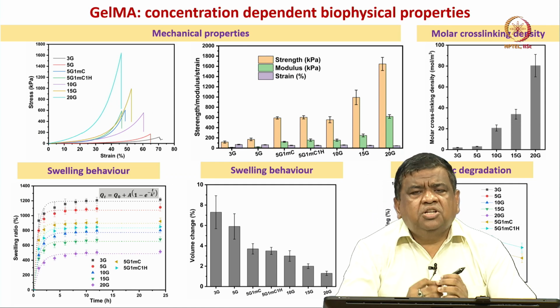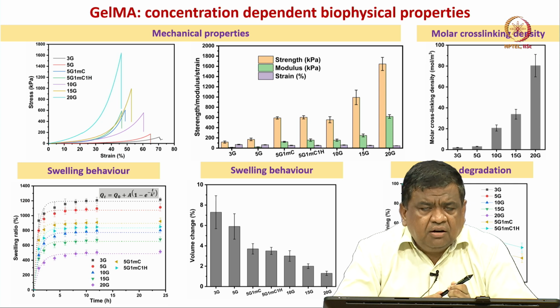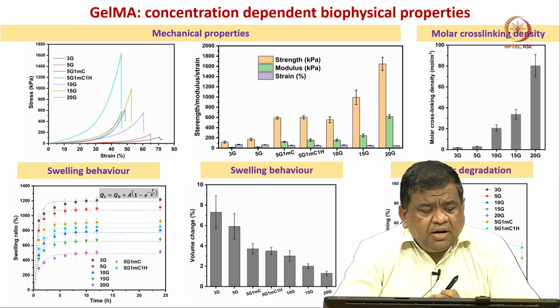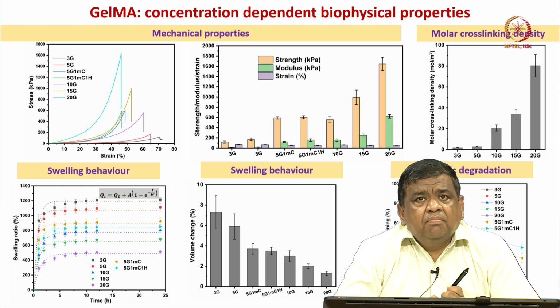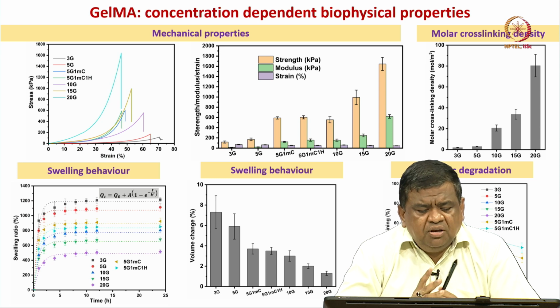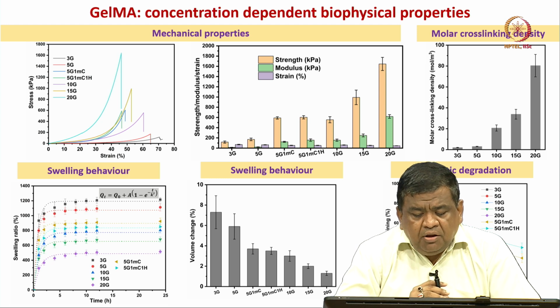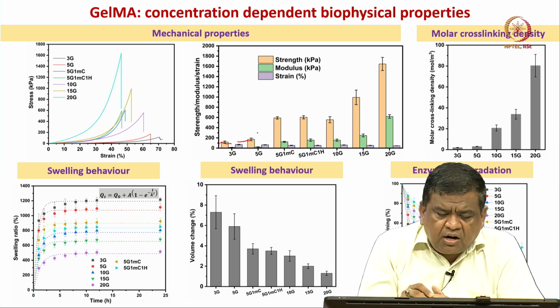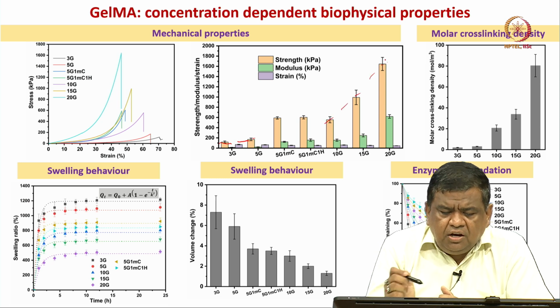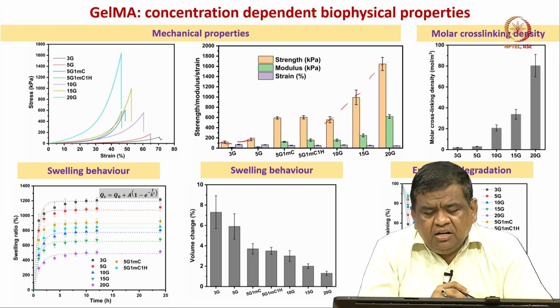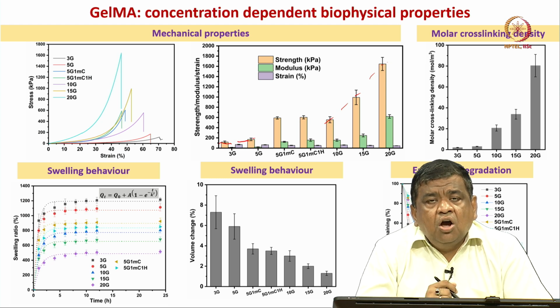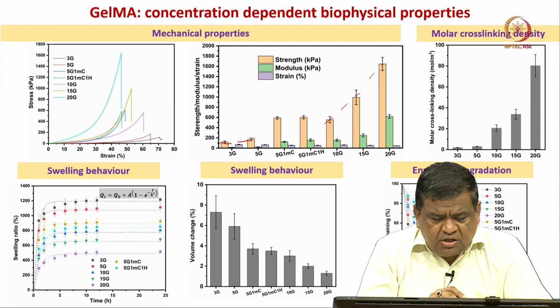So, gelatin GELMA, the first thing that we did while developing this kind of scaffolds, was to look at the concentration dependent biophysical properties, like when GELMA is being 3D printed with different concentrations like 3% GELMA up to 20% GELMA, how their properties vary. Now, if you look very carefully, if I make this dotted line 3, 5, 10, 15, 20, the strength actually increases with more concentration of GELMA, and that must be due to the molar cross linking density. So, the more the concentration of GELMA, the more is the cross linking density.